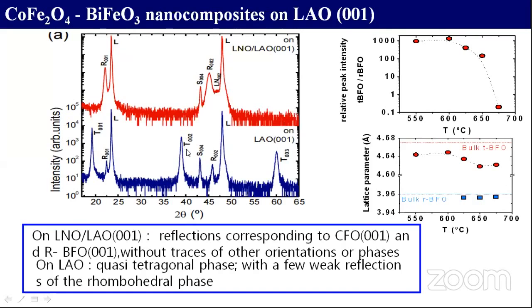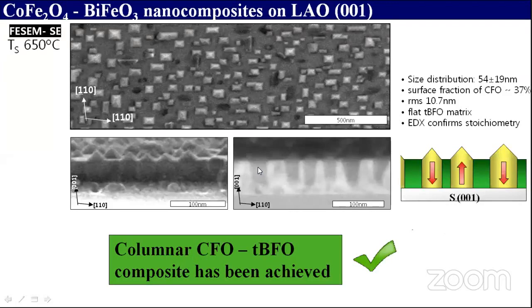This is quite new, because on a bulk scale, your bismuth ferrite will always be in the rhombohedral structure. By changing the in-plane lattice strain, you can tune from the rhombohedral structure to a tetragonal structure. I will just quickly show these SEM graphs, where very clean nanorods are seen, and this is the cross-section TEM, which clearly shows that we can have a clean interface of bismuth ferrite and cobalt ferrite.